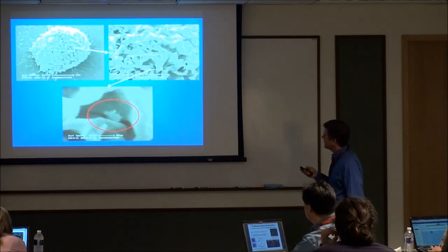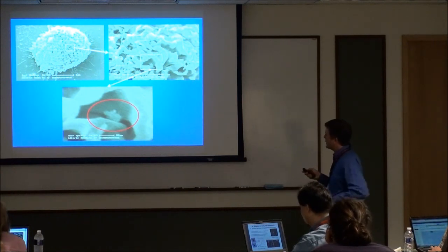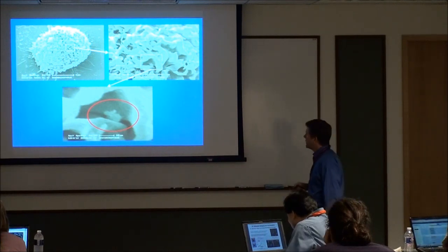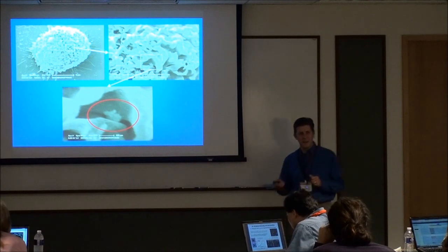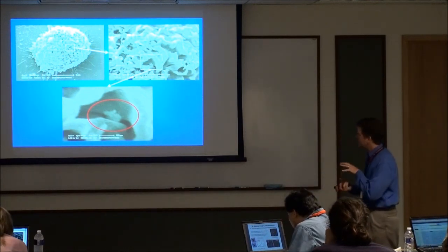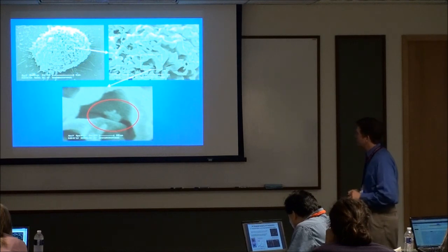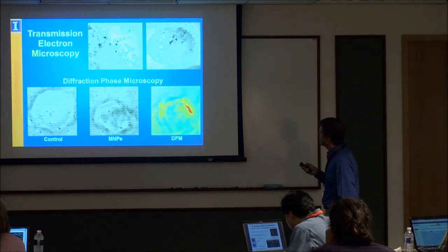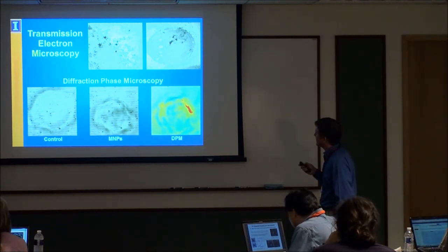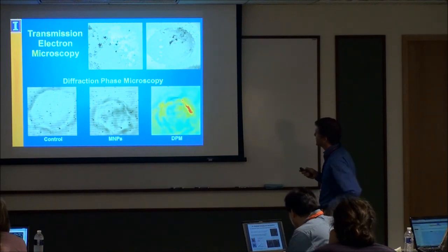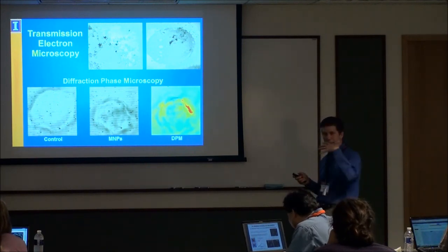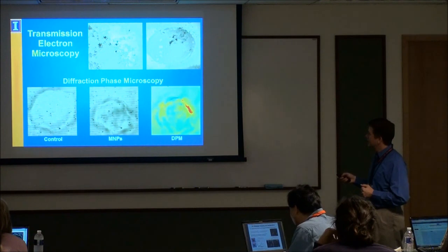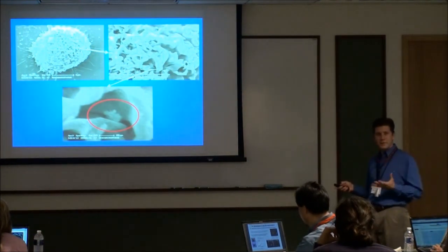So we think that we could identify very small, roughly 20 nanometer size particles. This is actually closer to about 200 nanometers. But this is our best guess at trying to find iron oxide particles on the membrane of these macrophages. We also did TEM, which gives us cross-section, and we can clearly see the iron oxide on TEM. That's the dark signals. And these have been engulfed by the macrophages, but then here are some iron oxide particles on the membrane. So this is our best attempt, we think these are the iron oxide particles on the membrane, and that's one from SEM.